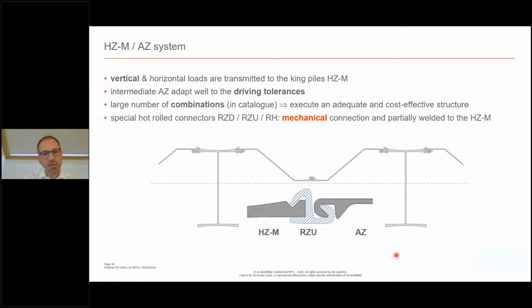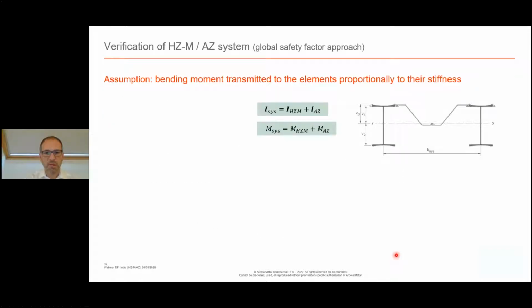The other advantage of a combined wall system, HZM, with the RH connectors is that you have a mechanical connection. So you partially weld the connectors to the HZ, but even if it would break for some reasons, you would still have a continuous wall, which is not the case for other solutions, also with the king pile walls and infill sheets.